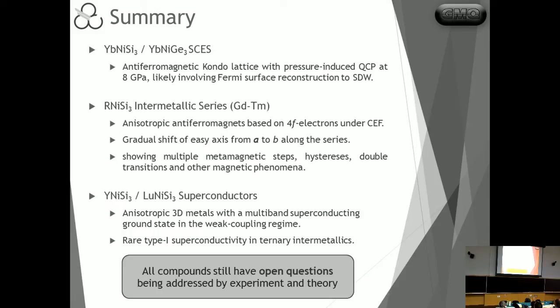So what I could gather from these 15 years working with this system. In the case of the ytterbium system, we have the antiferromagnetic Kondo lattice with supposedly a pressure-induced QCP at 8 GPa. And in this case, the Fermi surface reconstruction probably into a spin density wave. For the intermetallic series, these are highly anisotropic antiferromagnets. We see a gradual shift of the easy axis from A to B as we move along the series. And we have lots and lots of different features here that still require further investigation.